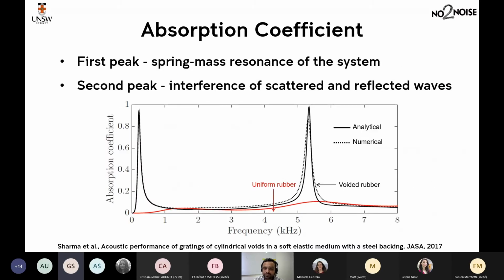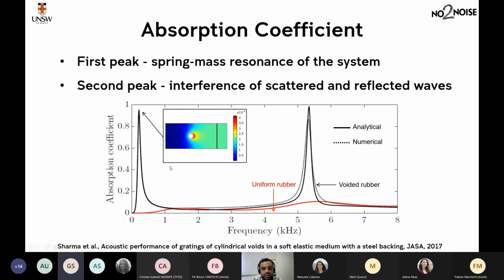Let's look at sound absorption now. So this is how the sound absorption looks. You see that there are peaks of very high sound absorption at certain frequencies when you have cavities in a soft medium attached to a rigid backing, right? And this is the sound absorption of a uniform rubber medium. As you can see, uniform rubber media don't perform very well, especially at low frequencies, right? The first peak corresponds to the mass spring resonance of the system. Here, the mass is provided by your steel backing and the stiffness is provided by your layer of voids. So that mass spring resonance creates a peak of very high sound absorption.